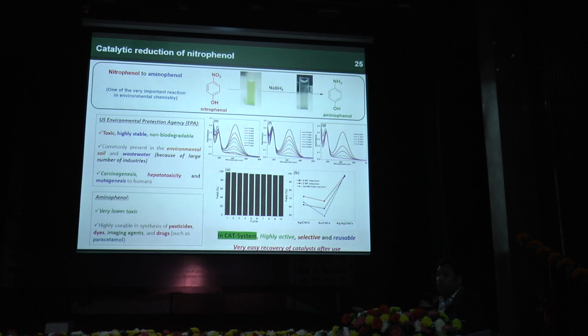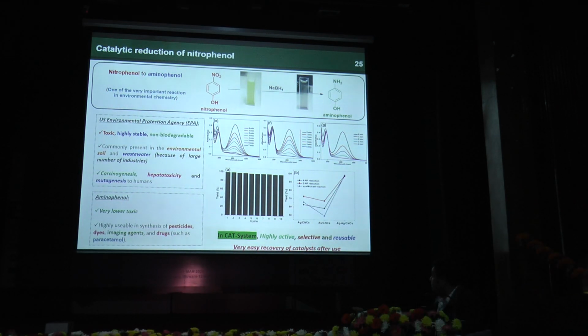So the same material we applied for conversion of nitrophenol into aminophenol because it is highly toxic. When you go for a textile industry, they often use this nitrophenol. So we wanted to convert this nitrophenol into aminophenol by using sodium borohydride. Our catalyst method is highly efficient. And the good thing is you can reuse it multiple times. Even after 10 times, the activity still remains intact.